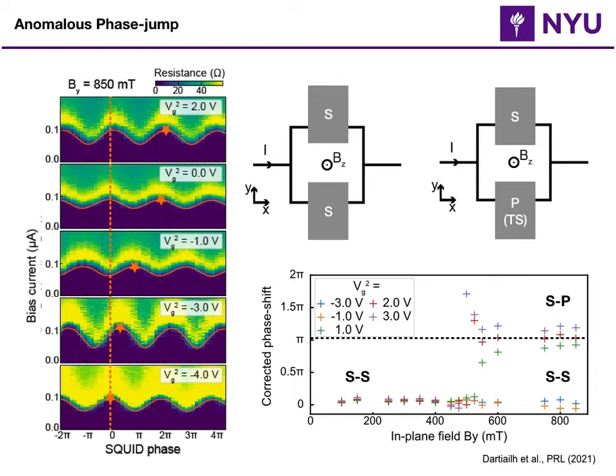Now we can keep one of them at a negative value and fix it, and we know it is S. But on the other junction, I can slowly increase the gate voltage, and at some point I will cross the boundary between S and P, and I will enter an S and P configuration. As you see here on the green symbol and red symbol and purple symbol, it's quite a drastic change. The moment we hit this transition, the phase actually jumps from 0 to pi, for all these values, and it seems to be converging there. It's a great signature because that's exactly what you expect from Majorana fermions if stabilized in a Josephson junction, and it matches the theory and expectation.